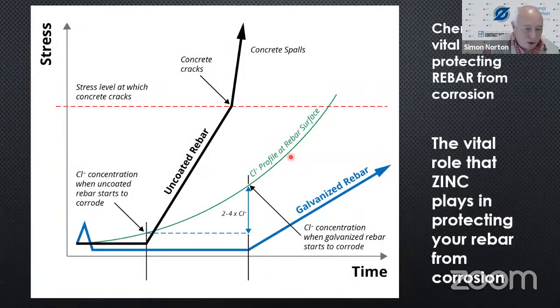Now, the other potent player in the chemistry that happens in concrete, because we're talking a little bit about that and it relates to zinc, is chlorides. Now, if you have a piece of uncoated rebar, and here on the green line is your increased profile of concentration of chlorides, at this particular point down here, the rebar starts to corrode, because of course you didn't design with galvanized rebar. Up goes the corrosion process, the stresses get greater and greater, eventually the concrete cracks and then